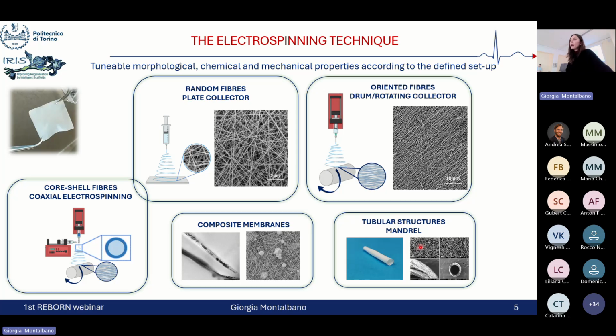tubular structures. Looking at the material formulation, we can also introduce some inorganic phases into the polymeric formulation that can be processed via a uniaxial system in order to promote their homogeneous distribution or the alignment into the fibers, or we can even exploit the simultaneous processing of two different polymeric systems using coaxial spinners in order to combine different materials and finally obtain core shell fibers.